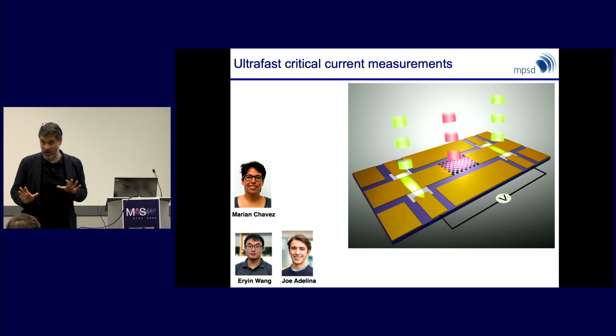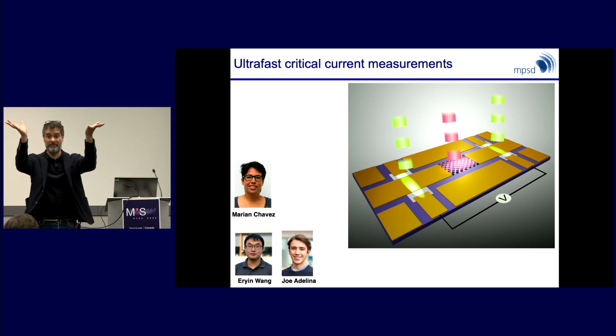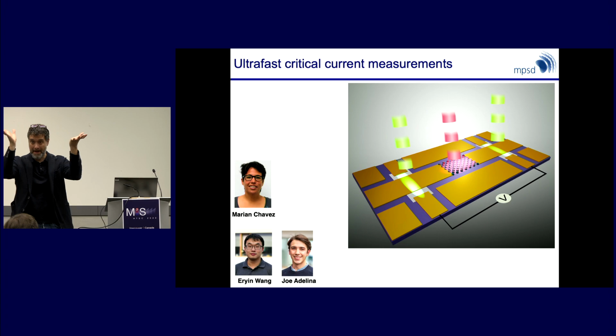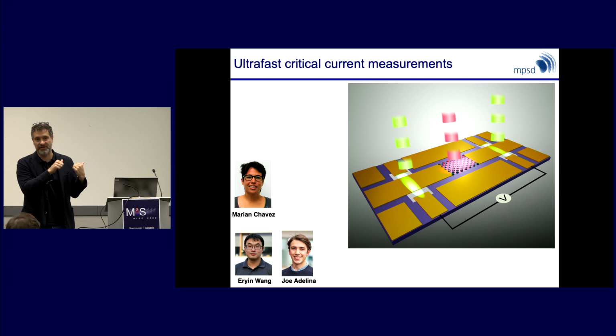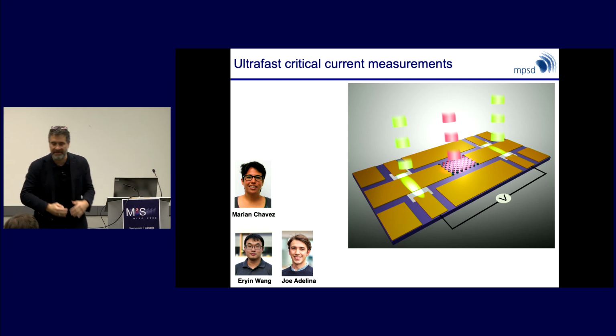What I think is going on, which of course I have no proof for, is that you create this photoinduced coherent state, and the rate-limiting step is the time scale needed to generate vortices in this state. In the same way that, if you take a Bose-Einstein condensate in the simplest possible case and heat it up promptly above the transition temperature, the rate-limiting relaxation time will be given by the time needed to generate vortices and antivortices. Because 2 delta excitations would be far faster than the time scale that we find. Let's say the hypothesis that is informing our experiment is this one. We have no way to prove it. Yeah. Thanks.